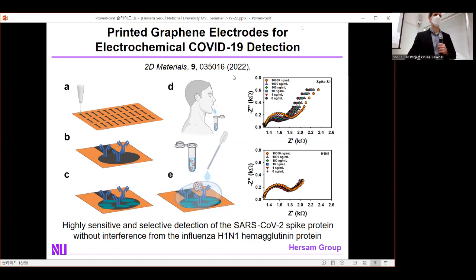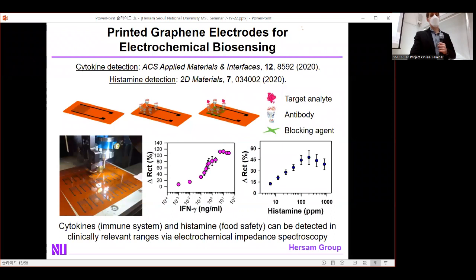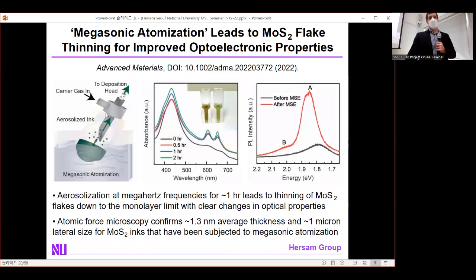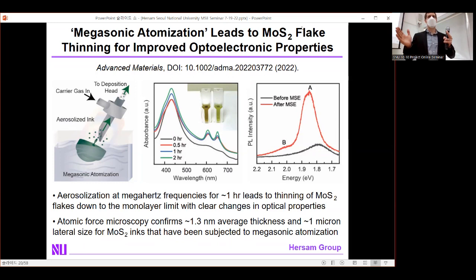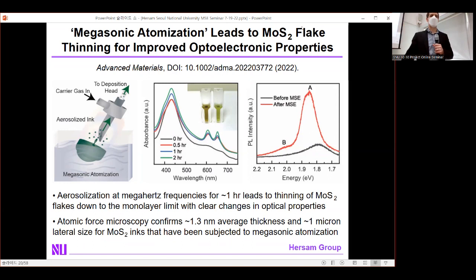Q: How did you get megahertz frequencies for the atomization? A: In the aerosol jet printer, the atomization process is achieved via sonication at megahertz frequencies. This is not uncommon in the semiconductor industry, where many sonication baths run at megahertz frequencies because bubble cavitation is more controlled than at kilohertz frequencies. This appears critical for thinning without chopping up the flakes — the controlled cavitation overcomes the typical trade-off of making flakes thinner at the cost of reducing lateral size, so you get very thin and relatively large flakes.